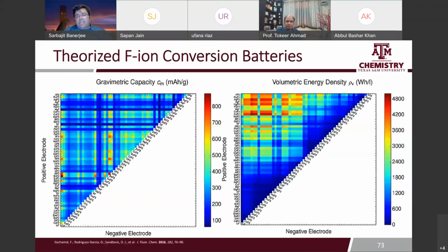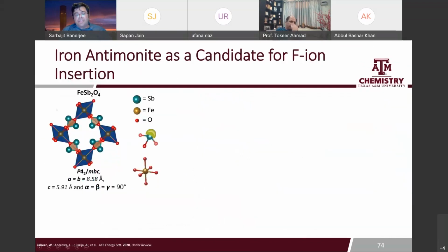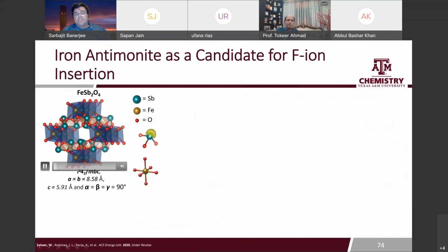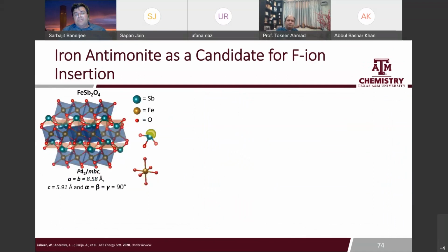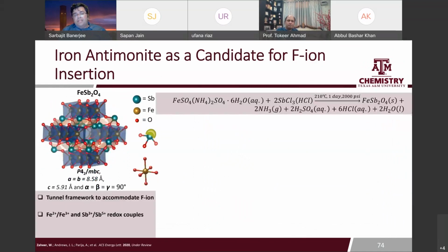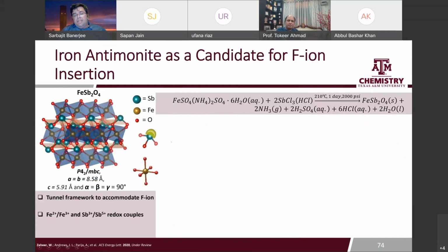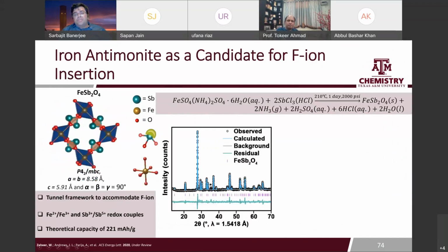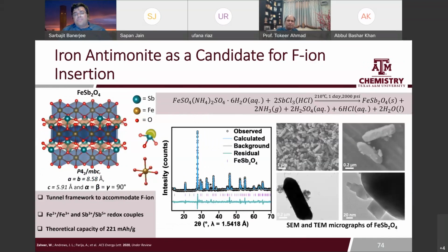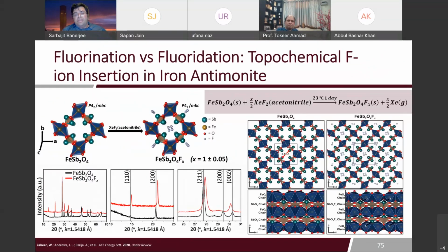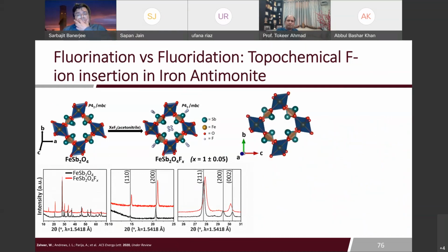There's relatively little in intercalation chemistry, and this is where we've done some work recently. This is actually published. I haven't updated the citation. This is a compound, iron antimonite, where it's got a beautiful tunnel in here, and it's got a lone pair on the antimony, and it's got its iron 2 oxidation state. The iron 2 can be oxidized to iron 3. This is phase pure, and again we can see this by X-ray diffraction. And here's the change in the lattice as it expands and contracts. Only slight distortions of the iron and the antimony.